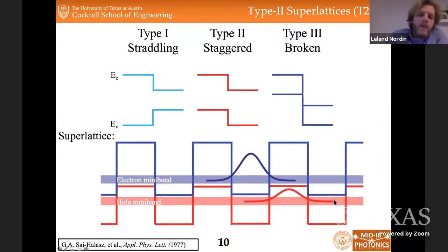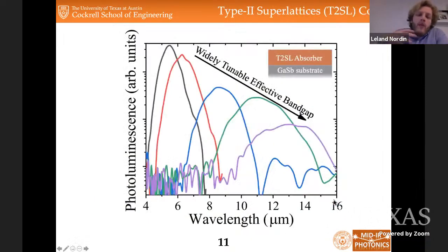And then the superlattice is if we stack these type 2 band offsets over and over again next to each other, we form a series of coupled quantum wells that are actually coupled via tunneling, and you can form electron mini-bands and hole mini-bands whose effective band gap can be narrower than the constituent materials. We have grown a lot of these, and as you can see, we're able to tune this effective band gap across the mid-infrared, no longer being bound by the constituent materials' band gap.